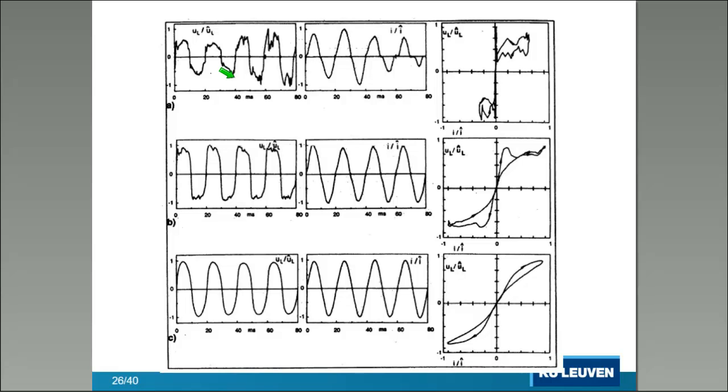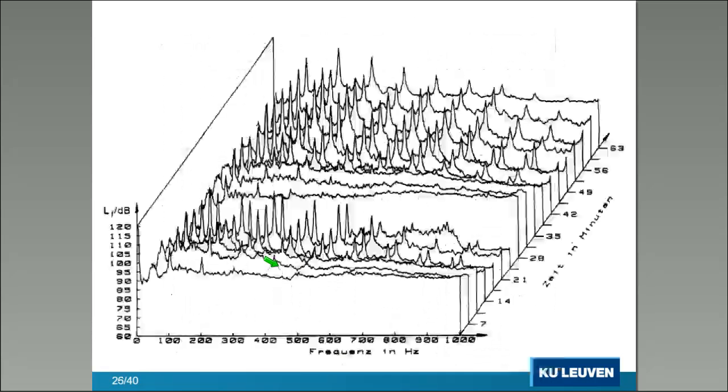You see that the voltage of the system is very random. Remember the noise, which was at the beginning also very random. And here it becomes better when the process progresses. And at the end of the process, you have a purely resistive kind of heating. That means a very smooth manifestation of current and voltage.